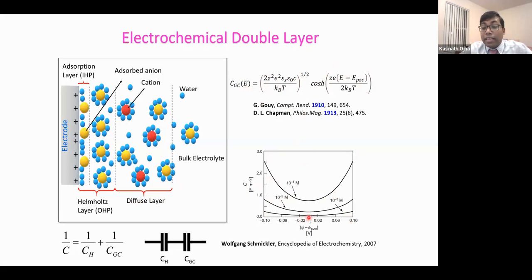And at the potential of zero charge, when E equals EPZC, then you get a minimum value of the Gouy-Chapman capacitance. And that point, we call the potential of zero charge. So basically, this is a classical method to find the potential of zero charge of an electrode. We can change the potential and we can change the concentration of the electrolyte, and we measure the capacitance value. And wherever we see a minimum in the capacitance curve, at that point we can say that is the potential of zero charge.